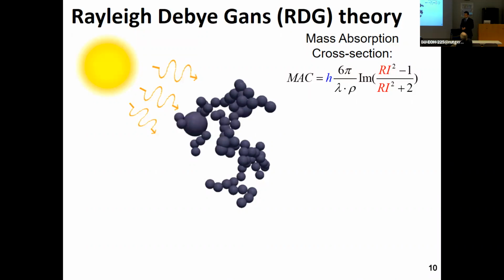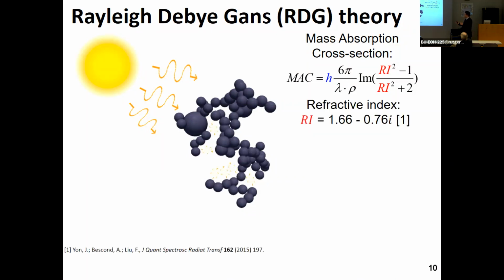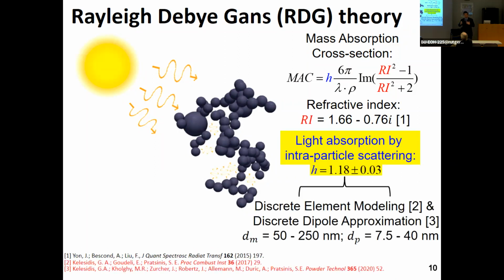So we use the model that I described to you earlier that accounts for the realistic morphology of black carbon. And we interfaced it with the Rayleigh-Debye-Gans theory to get, first of all, this property, the mass absorption cross-section, which quantifies the light absorption only for one nanoparticle, only for one agglomerate. I won't go through the specifics over here for the sake of time, but again, if you have questions, you can let me know. The main point that I want to convey is that the light absorption of these agglomerates is enhanced by this factor, this 1.18, because the light is trapped in this porous structure of these nanoparticles. And because it is trapped, it enhances the total light absorption by this agglomerate.